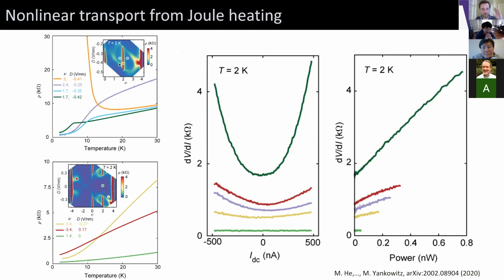I hesitate to make that claim about what it is in general, but for the samples that we've measured, we have not seen anything that's characteristic of superconductivity. There's a few things that we can judge. One is that we don't see quasi-particle peaks or a saturation to a normal state resistance. Another is that we don't see a sharp change in the resistance above some critical magnetic field. And the last thing is that we don't see Fraunhofer oscillations, which are basically unavoidable in these van der Waals heterostructures owing to disorder. So you end up with pockets of superconductivity and normal metal states in these samples. And then the critical current will oscillate, and we don't see anything like that. So by those metrics, no.